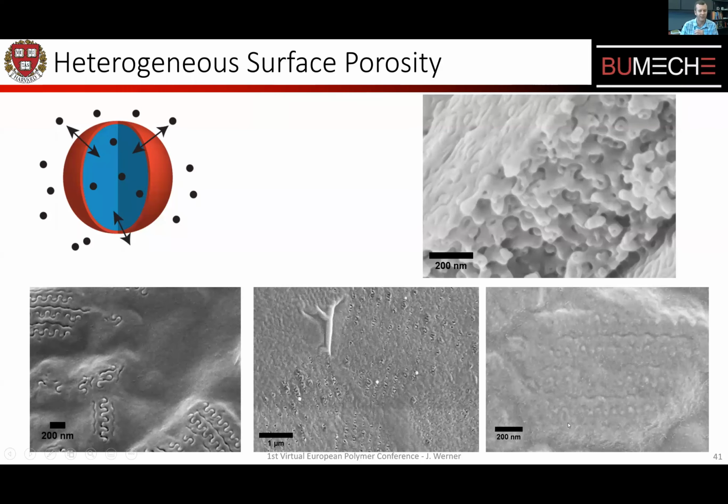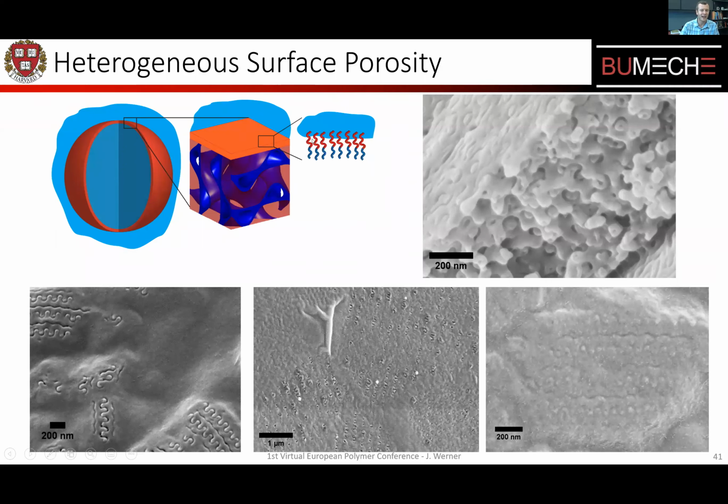Of course, we couldn't look at every capsule all the way around in SEM, but we assume that there's quite a bit of heterogeneity in these capsules, even though they're all made through this continuous same process of microfluidic templating. There are quite a few capsules that have this capping layer, which is known from thin film solid polymer self-assembly at the water-oil interface, and therefore block diffusion into these capsules at any pH. So this is something that still needs to be addressed to be able to allow these to be 100% functional or homogeneous.